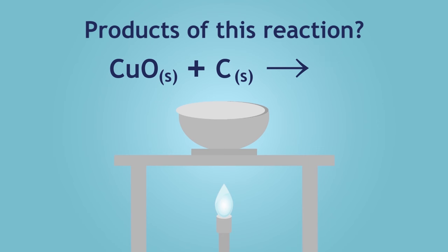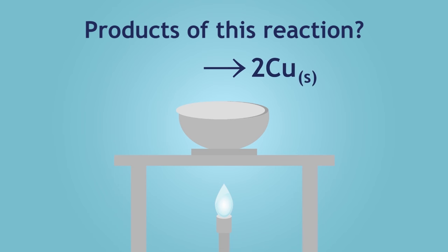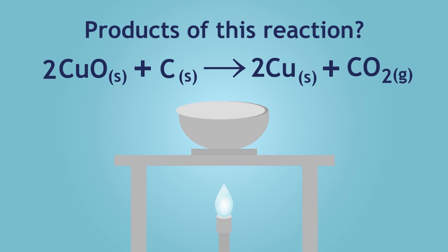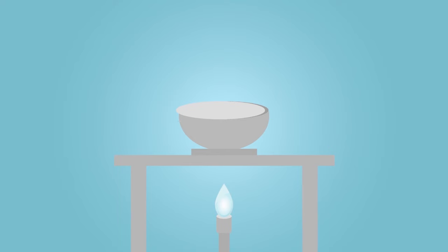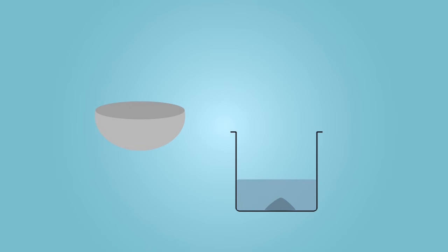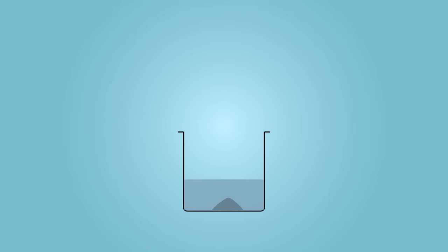The carbon displaces copper in copper(II) oxide to give copper metal and carbon dioxide. Remove the crucible from the Bunsen burner and empty its contents into a beaker of cold water. Pour out the water and charcoal, rinse with water, and repeat. This must be done while the mixture is hot, or else copper(II) oxide will reform. You will find little bits of copper metal at the bottom of the beaker — you have successfully extracted copper metal.